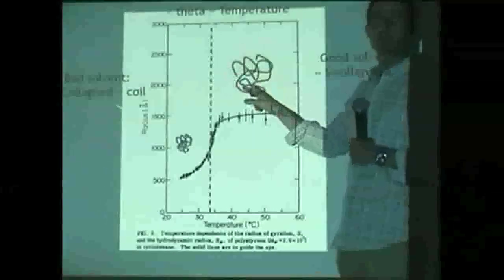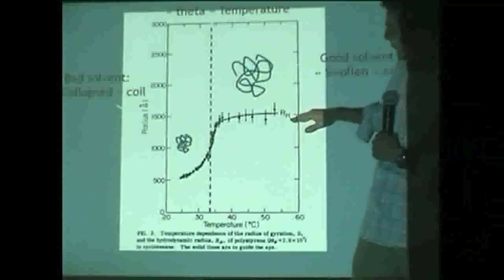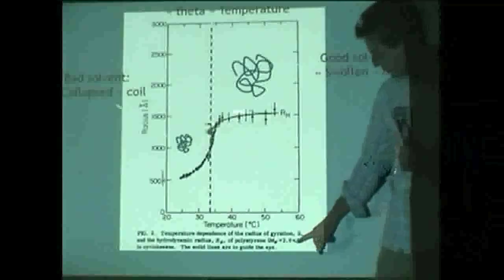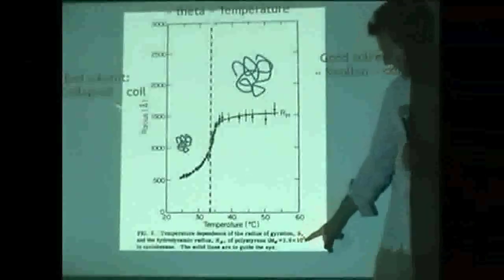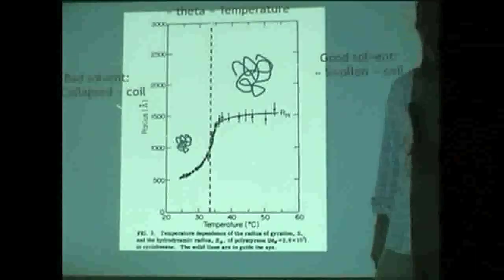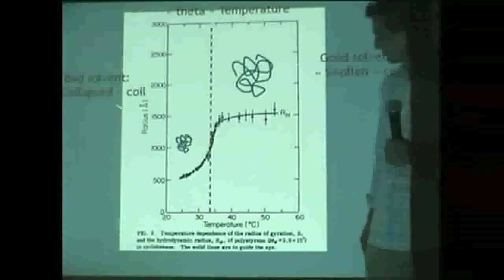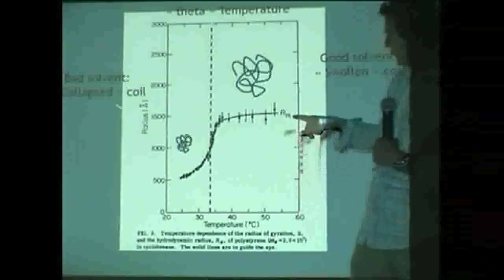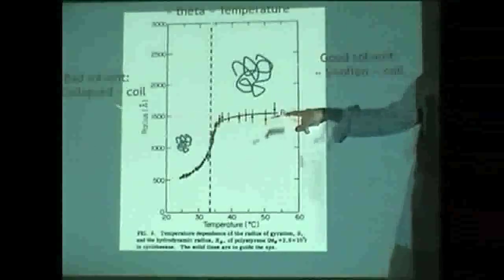And they have measured the gyration radius of the sphere, of the polymer chain. And what they find, for example, this is a polymer of mass 2.6 times 10 to the power 7. Do you remember, this is 26 million grams per mole. So this is a very big chain, okay? And for this very big chain, they find that the gyration radius is 150 nanometers, okay? 1,500 angstroms.